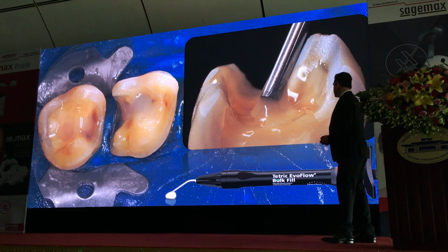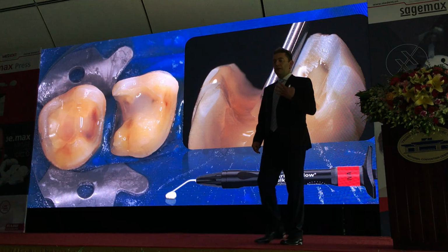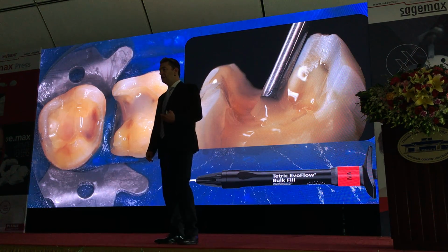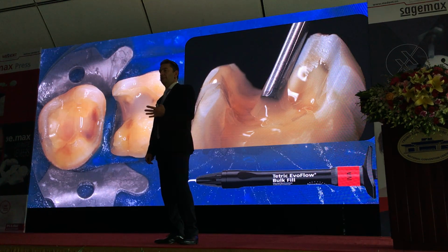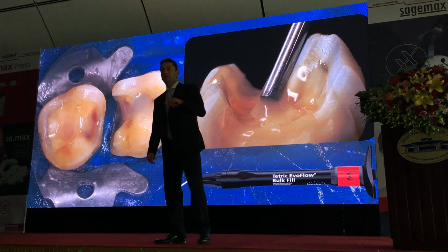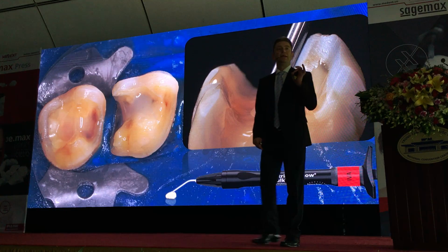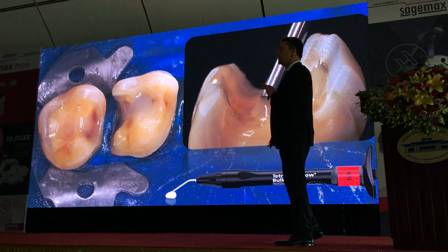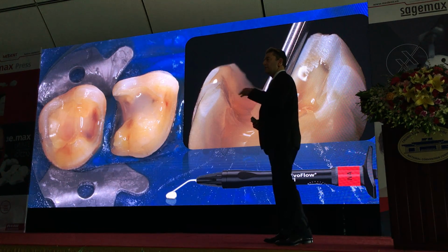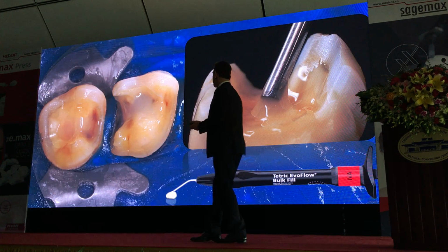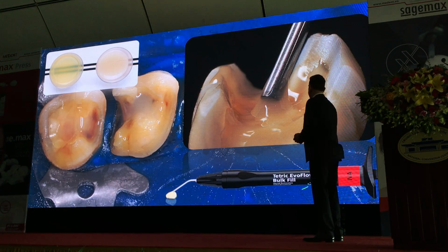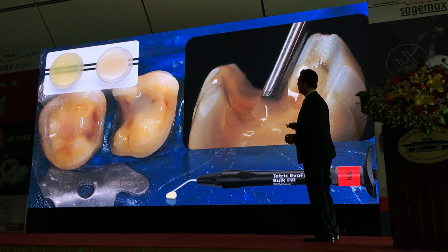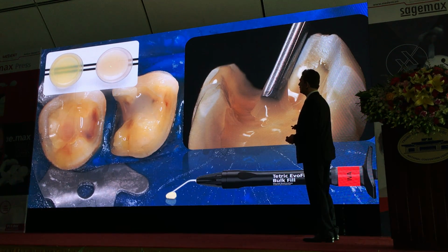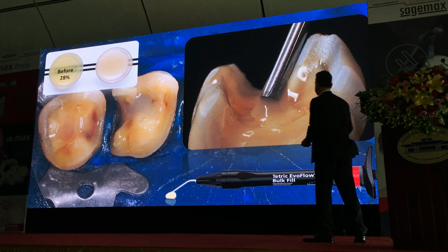So here, of course, when you do this with the composite, you should make sure that you use a material that has a high radiopacity so that you can see this on your X-ray, right? Because if you have a thin layer of composite or anything, you need to make sure that it has a high radiopacity, and Ivoclar composite materials contain a special filler that makes the material visible on the X-ray. Yeah? Okay. And this material here is very special because before curing, this is a Tetric EvoFlow Bulk Fill. Before you cure it, it's translucent. After you cure it, it becomes opaque. Okay, it's just like dentin.